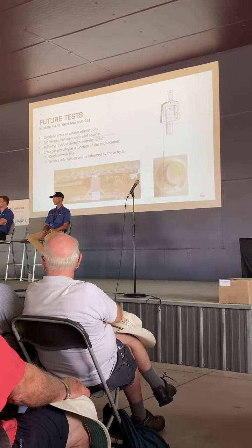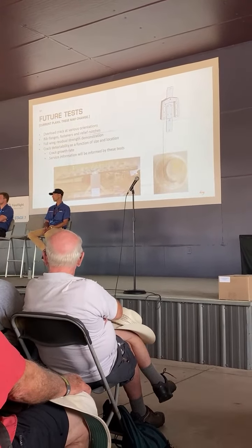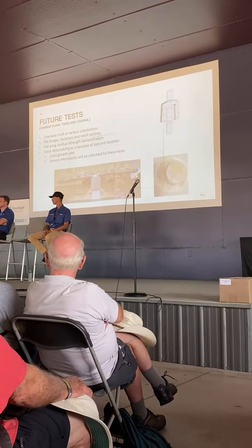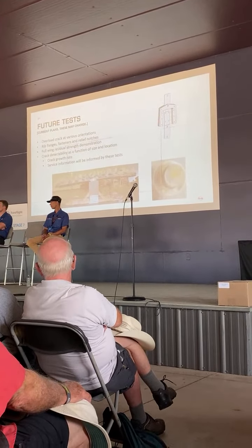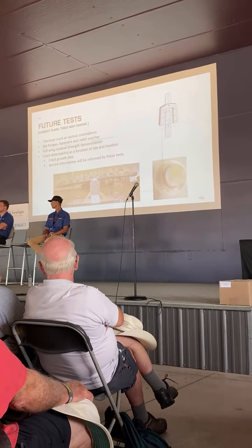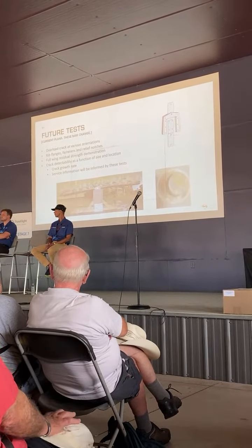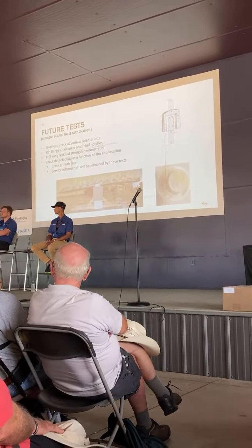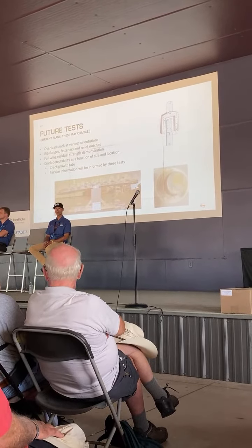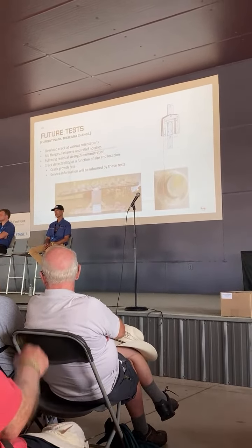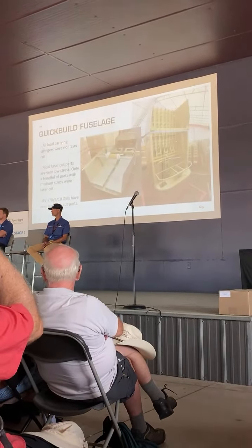The full wing residual strength demonstration. So we're just going to demonstrate the strength of the wing, which is really showing compliance to that FAR. There's also a later FAR that we're aware of as well. In comparing ourselves, that's a Part 25 requirement. We're using it as guidance. Crack detectability is a function of size and location. So if a crack would grow, how fast is it going to grow? And from what we've known so far, that is, if it ever did grow, it would grow very slowly and be detectable. We don't want to just say that. We want to prove that. So that's further testing that's going to go on there.